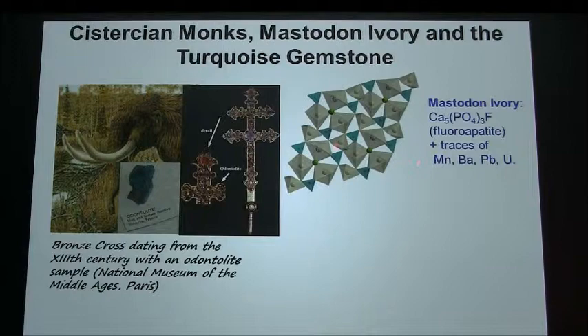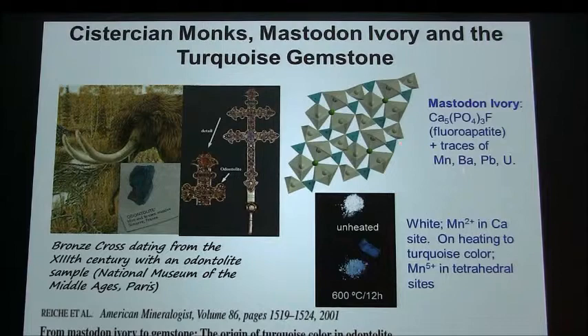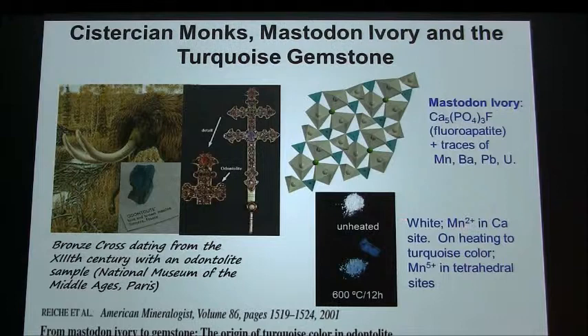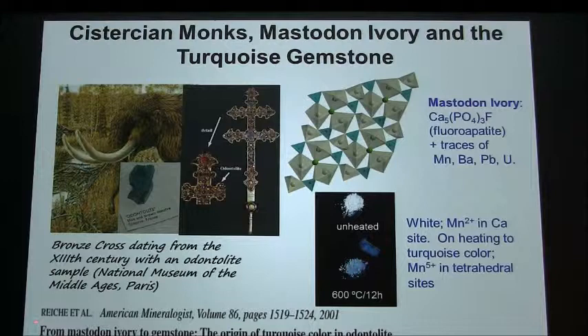When they heat it, some of the manganese goes into the crystal structure, becoming manganese in the 5+ oxidation state. When it is manganese 2+, it is white. When it is manganese 5+, it becomes blue. Then it becomes like a turquoise actually. So you can see there's a nice publication by a geophysical lab in the American Mineralogist journal. They published "From mastodon ivory to gemstone: the origin of turquoise color in odontolite." So when I read this, I was thinking, maybe there should be a way we can create our own artificial turquoise pigments.